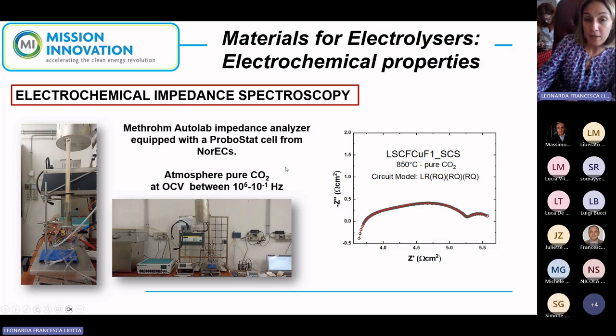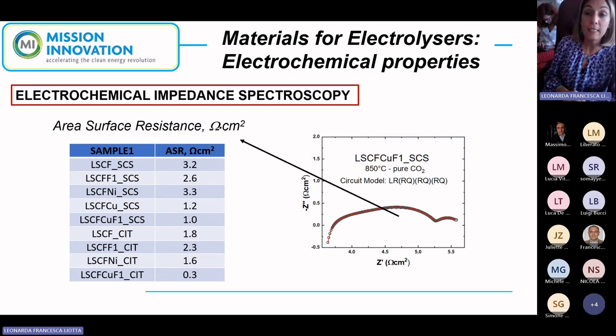Our tests were carried out in pure CO2 at OCP, and the data reported here is a Nyquist plot where we have the real component of the impedance, and here the imaginary component of the impedance. These are a series of semicircles. Each semicircle corresponds to a specific circuit element.